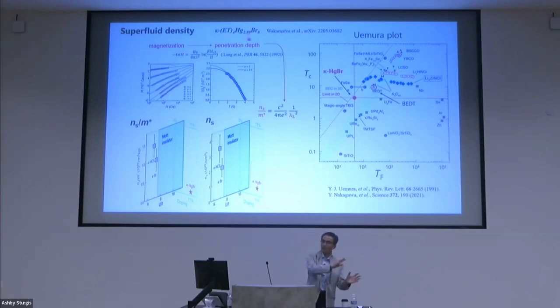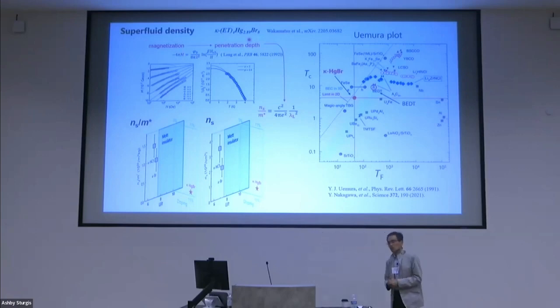But in other materials, spin liquid candidates, disorder is an issue. In my opinion, for example, the data of the spin susceptibility does not show any tail. The paramagnetic impurity is minimized, maybe roughly less than 10 ppm. The systematic materials are very clear. Anyway, it's an issue, I think.